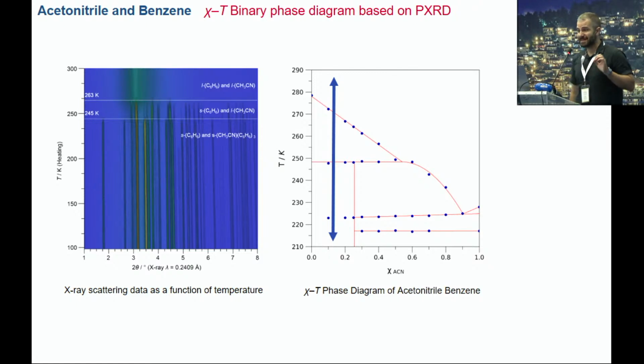First of all, we see exactly the same information that we see in the phase diagram derived from DSC. At the top of the diffraction patterns, we can see no scattering, which makes sense, because at the top of the phase diagram we have liquid. Then in the first region, the triangular one, we have scattering from one phase, and the rest is liquid, which doesn't scatter. And down there, in that rectangular shape, we have two phases. This is already quite a lot of information. However, it's still not complete.